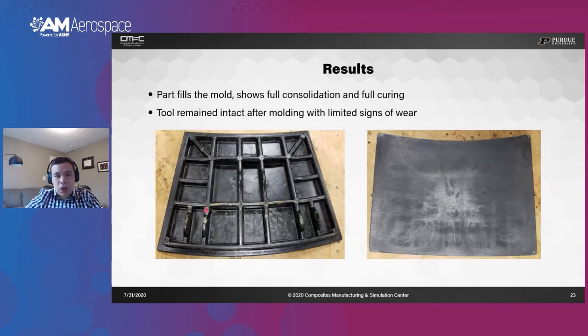So overall, the mold cavity was filled completely. There are some areas that are resin rich, but this was the first trial we did, and these resin rich areas can be overcome by improving the processing conditions. But overall, the molding process was successful.